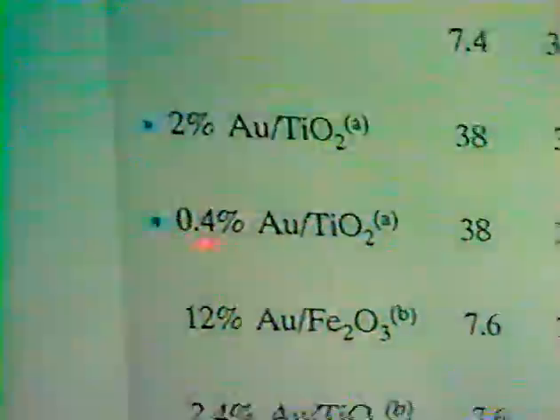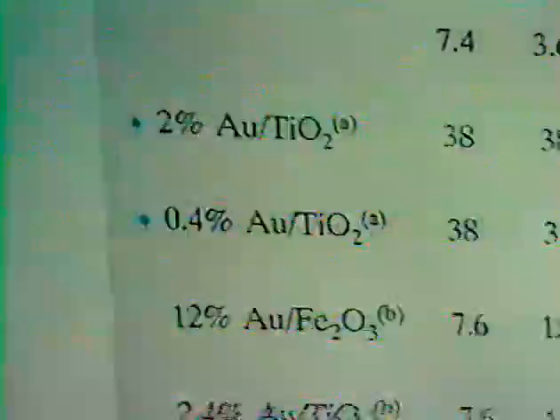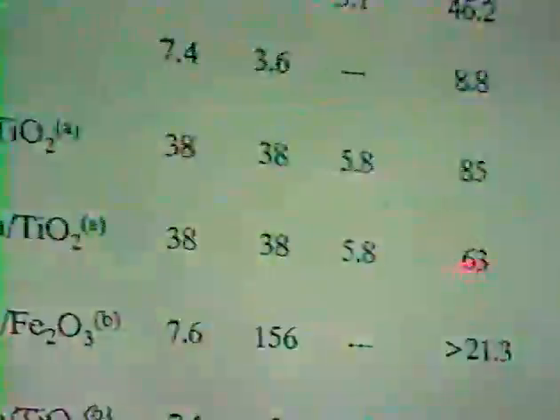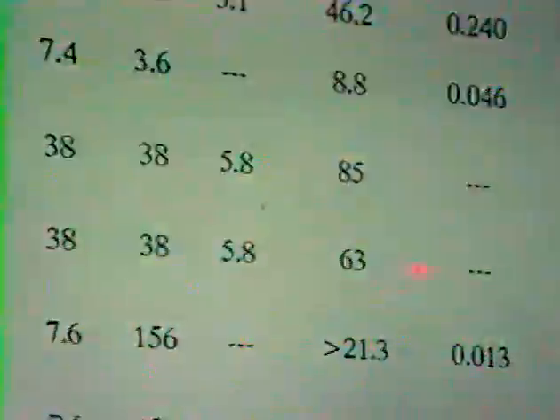Most recently, we have looked at the catalyst represented here. We prepared another batch of the 2% gold and titania. We have found that this catalyst is even more active, as shown here. It also has extremely good activity maintenance. As of the time I left, we had done partial pressure studies and Arrhenius runs with no loss in activity. This catalyst will convert CO at ice water temperatures and probably below. It's just we have not yet gone below 0 degrees centigrade.